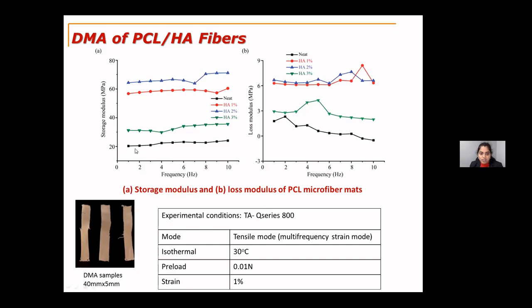As we can see, the storage modulus of the neat fibers is around 20 megapascals, but infusing the nanoparticles has increased this to 70. That means it increased up 3 times, similar to that of the tensile strength. Here also we can see that the hydroxyapatite with 2 weight percent has higher storage modulus compared to that of 1 and 3. So the 3 has the least compared to the 1, 2 and 3 weight percentages. However, infusing the nanoparticles has definitely increased the storage modulus compared to the neat polymer.